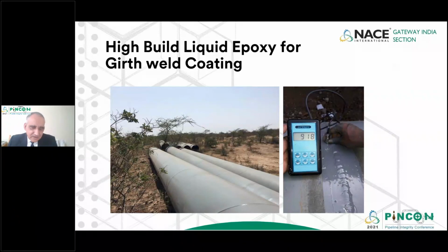Now, moving a little bit after the line pipe coating: when the piece of pipe is coated in a factory, it's called line pipe. It's a standard 12 meter. But these pieces of pipe have to move to the site for construction of a longer pipeline, and then they are welded together. It's called girth weld. So the girth weld area, which is also called field joint, also needs to be coated with a corrosion protection coating. And the material should exhibit the same level of corrosion protection performance which the line pipe FBE or DFBE coating is doing. So each manufacturer has a compatible high build liquid epoxy coating, which can be applied easily in the field, and it also gives you similar performance.